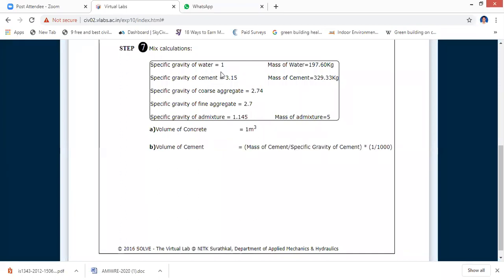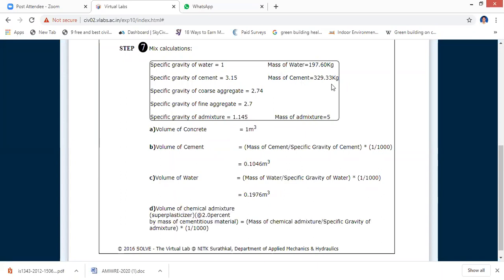Specific gravity of cement is 3.15. Specific gravity of coarse aggregate is 2.74. Specific gravity of fine aggregate is 2.7. Specific gravity of the admixture we used is 1.145, right? And mass of water is 197. Cement is 329. Admixture is 5. So based on that, it calculated all the content required to design 1 cubic meter of M15 grade concrete.